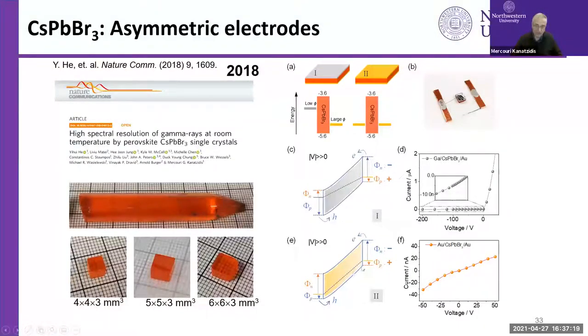At first, we thought the material was not good. We spent a lot of time trying to make it better. However, we then realized that this high current may not be because the material is not good, but because if you look at the energy difference between the gold work function and the valence band position and conduction band position of the perovskite, in one direction the gold has a very, very low barrier. And in the other direction, as we bias it, it has a very high barrier. So no matter how we bias this thing, one side has low barrier energy and it injects electrons. And this was the source of the high current. Not because the material was not good.